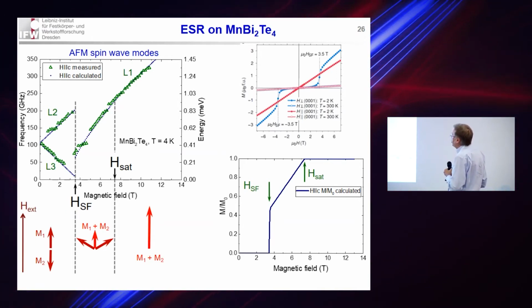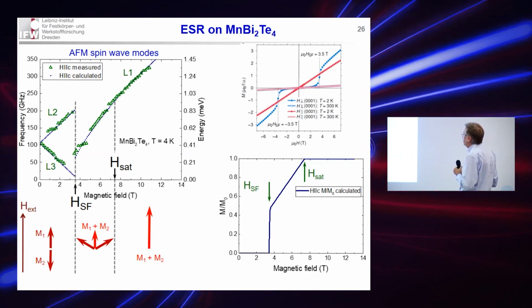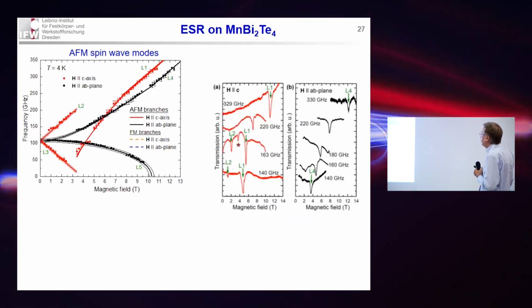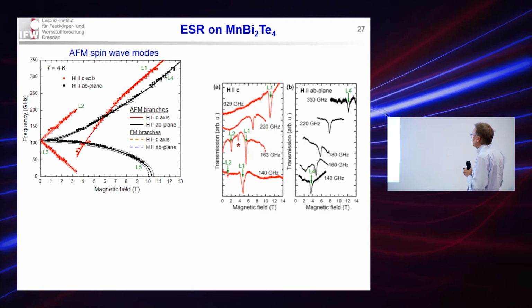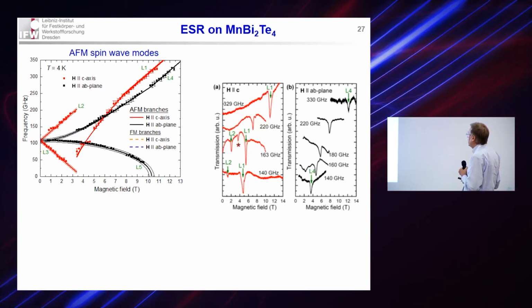Actually, when we change the orientation of the field from out of plane to in plane, we have a completely different excitation spectrum. These are two modes, this one and the other one which we observed.